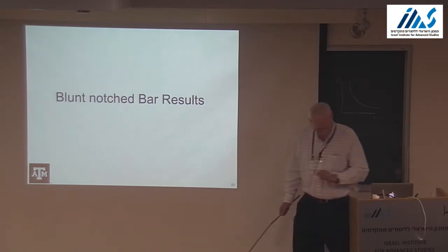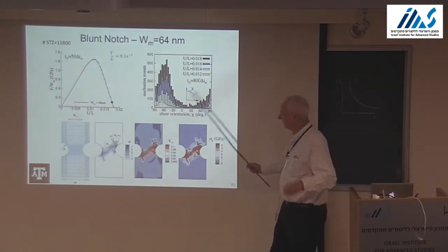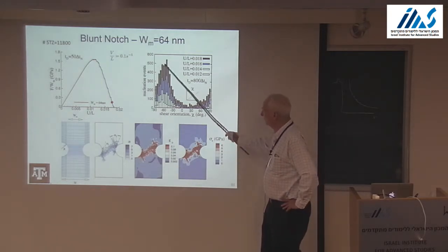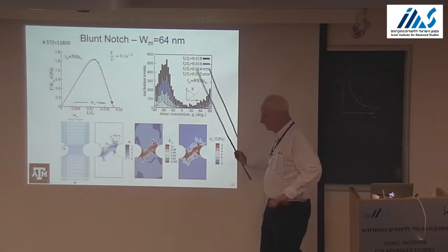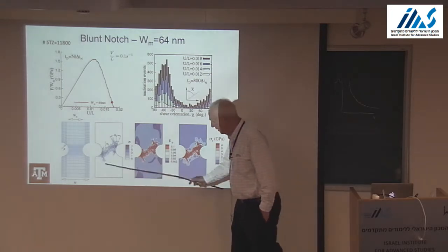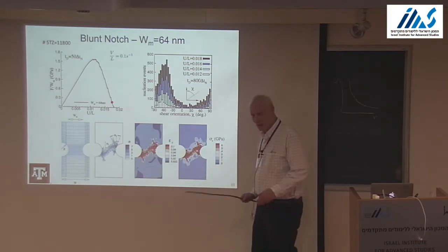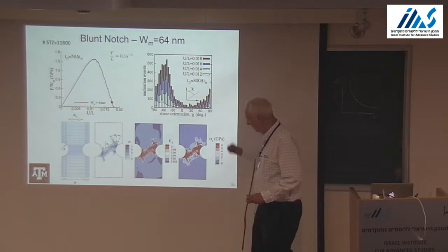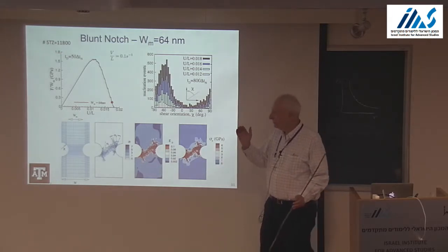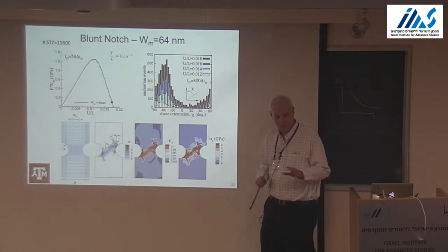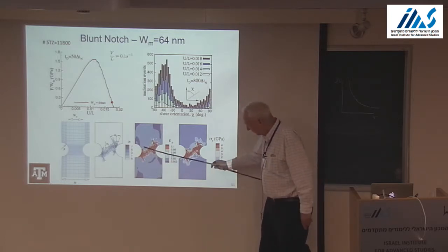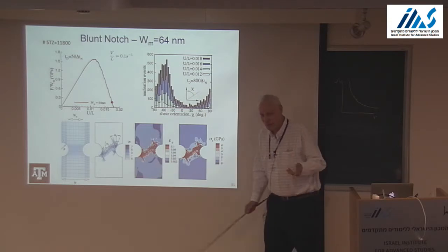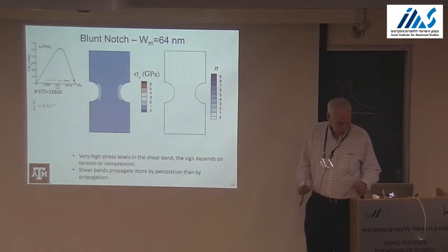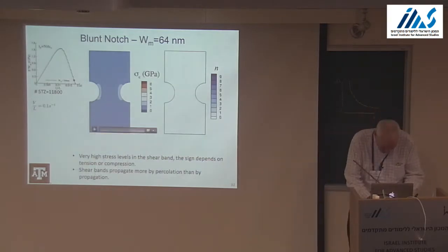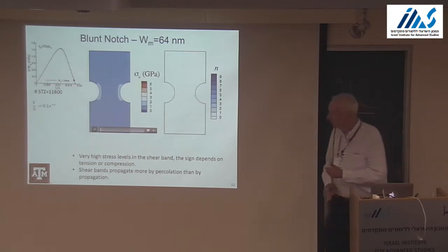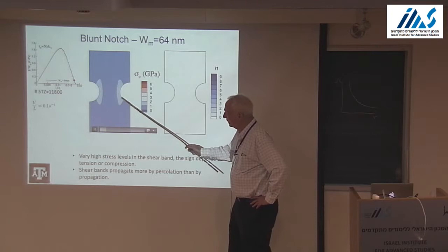Now we go to notch bars. I'm almost done. One thing that happens there, just in case you see, the orientation spreads out because of the stress gradient, but you get shear bands that form. Again, the shear bands start, and it really looks just about like the slip line field theory, not quite perfect plasticity. But then, of course, that would be symmetric. The statistics breaks the symmetry, and you get one band that dominates. I think I may have a picture here. I'll do one of these movies. I won't do two. But you see the stress is increasing.